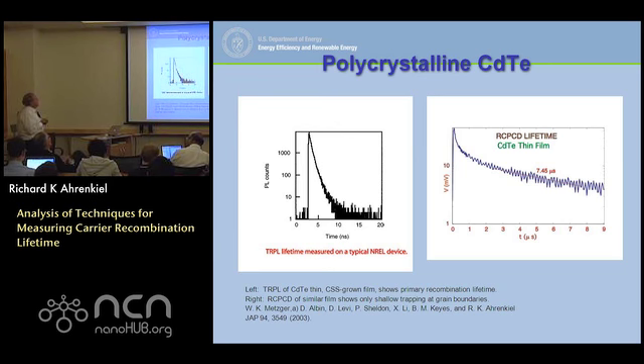Now, here's one of the problems with shallow traps. This is the polycrystalline cadmium telluride that's used in solar cells, grown at NREL by what's called the CSS technique. The standard way to measure carrier lifetime is TRPL, and typically we will get 2 nanoseconds or so in the best films. That's the best we see. And if you remember CIGS, we got 100 nanoseconds, which is, I think, why CIGS is surpassing gallium arsenide by quite a ways in terms of efficiency. But this is what we see in TRPL. Now, there's a little residual signal here, but you can barely see it.